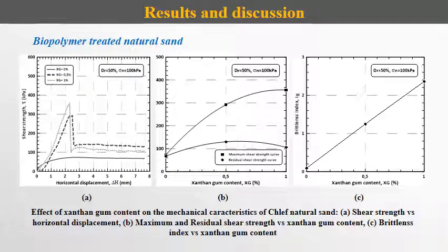The following figure presents laboratory results of direct shear tests on biopolymer treated sand prepared at medium relative density and at a normal stress of 100 kPa. From the figure, it is noted that biocemented sand samples show brittle behavior with an apparent peak in the stress-strain curve. A considerable increase of maximum shear strength is observed with an increase in xanthan gum content.